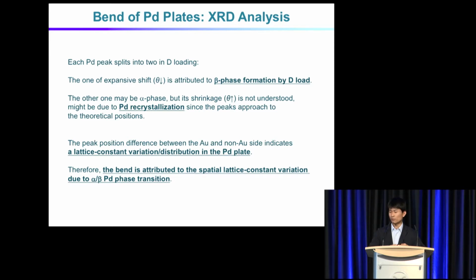Probably due to the palladium recrystallization during our experimental runs, but the temperature may not be that high, so we are still wondering. And the peak position difference between the gold and non-gold side indicates a lattice constant variation or distribution, so some profile of the lattice constant exists inside the palladium plate across the thickness of the plate. And therefore, the bend is attributed to the spatial lattice constant variation due to the alpha beta phase transition.